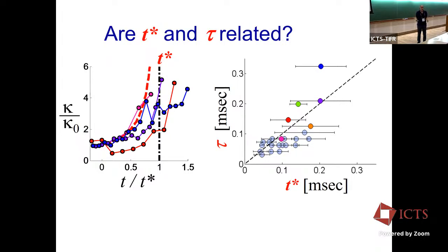The last thing that I wanted to tell you is that, well, let's go back to the beginning and I'll summarize what we talked about. First, we looked at the oscillatory instability and saw that for an infinitesimal shear perturbation at a critical velocity, an oscillation takes place.